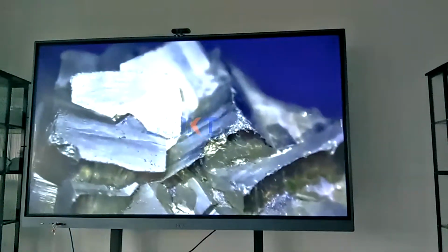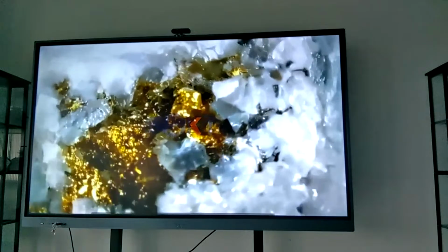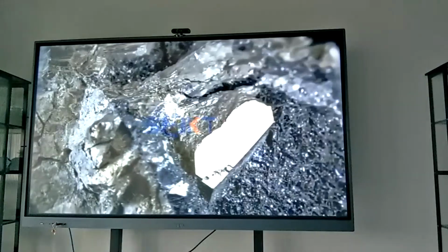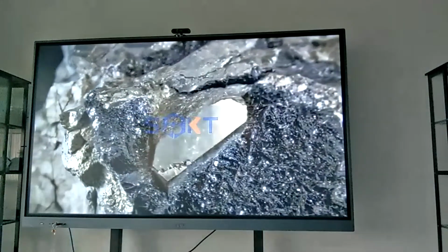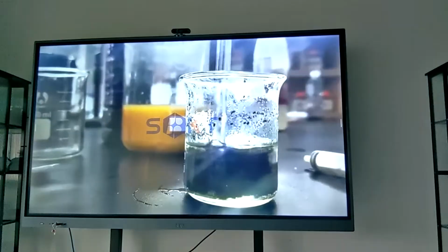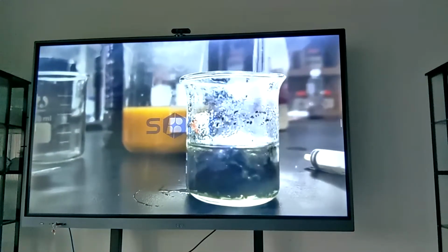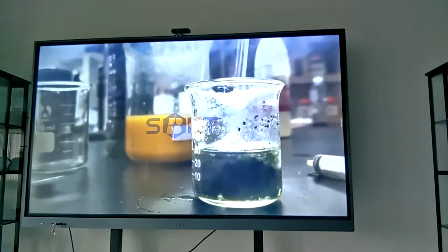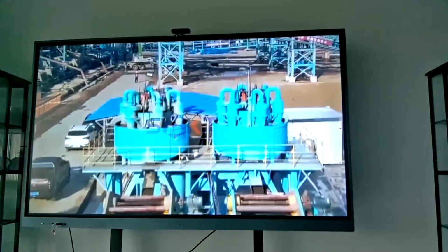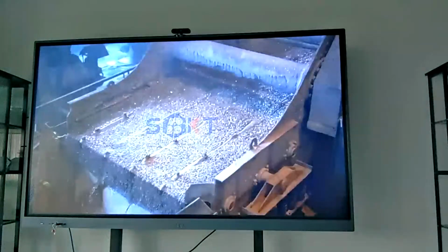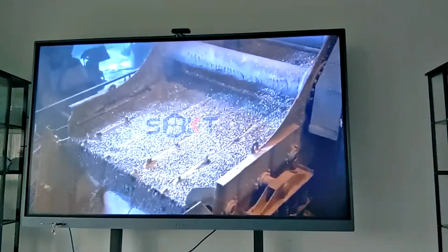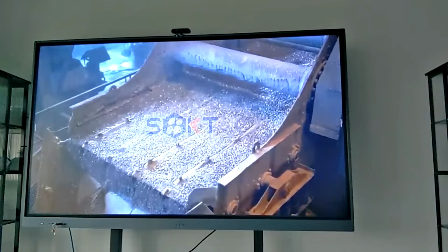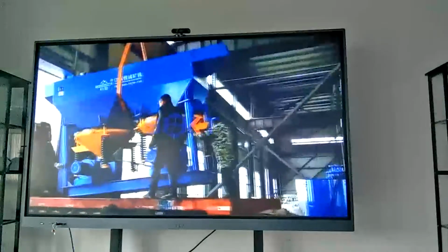Sixth part is placer gold deposit, a physical separation. Characteristics: gold is liberated, has a large density difference, and does not contain chemically oxygen-consuming substances. Process selection: the only method is gravity separation, jigs, sluice box, shaking table. Completely cyanide free. Physical methods offer efficient, environmentally friendly, and low-cost recovery.